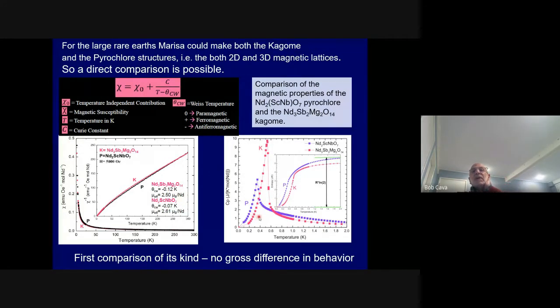Eventually, these materials order at low temperature, and you can see that in our world by looking at the heat capacity as a function of temperature. You can see that the Kagome orders at this peak, which is the loss of entropy where you have magnetic ordering, so it shows up in the heat capacity. And so the Kagome orders at a slightly higher temperature than the pyrochlore, so the 3D system is more frustrated. The thing I want you to notice about this is there are some really low temperatures involved here. This is like a half a Kelvin, and this is like 0.3 Kelvin. So these things are really low.